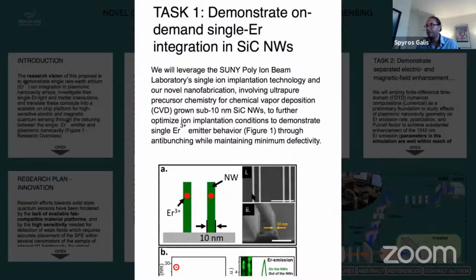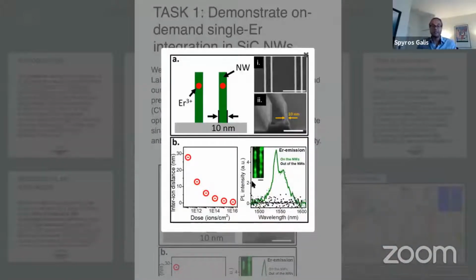We have successfully demonstrated integration of an ensemble of erbium ions into ultra-thin nanowires, 10 nanometer. And another key property of these nanophotonic structures is that they exhibit an absorption cross-section for erbium ions which is 2 orders of magnitude larger than typical benchmark values in erbium-doped bulk materials. This is another important photophysical property, which was enabled by our novel nanofabrication, reduction of defect density, and also device design.